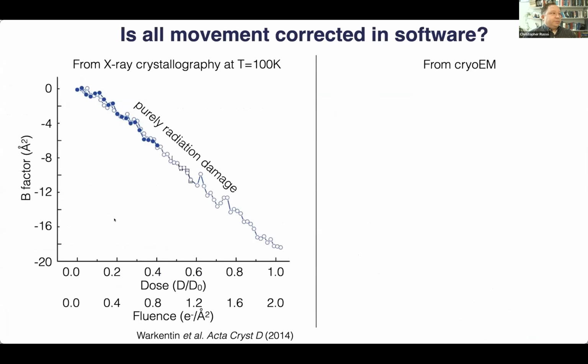Well, we know this because there have been lots of studies of the damage to molecules using X-ray crystallography at the same temperatures that we use for our cryo-EM. And in all of these, you can see that the information, in this case characterized by a B factor, or Debye-Waller temperature factor, which is basically how far out the atom is blurred from its original position, this is entirely linear all the way back to extremely low doses.